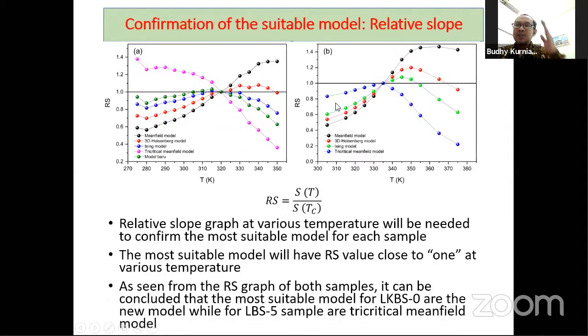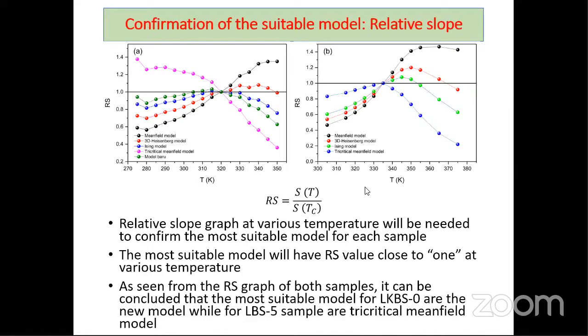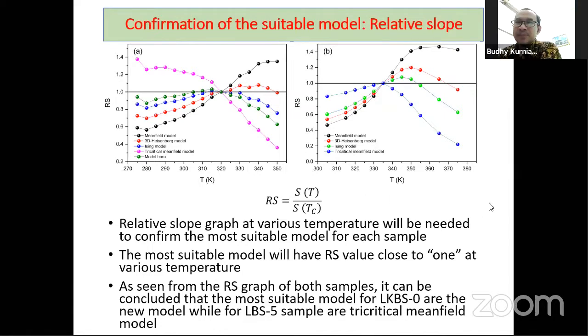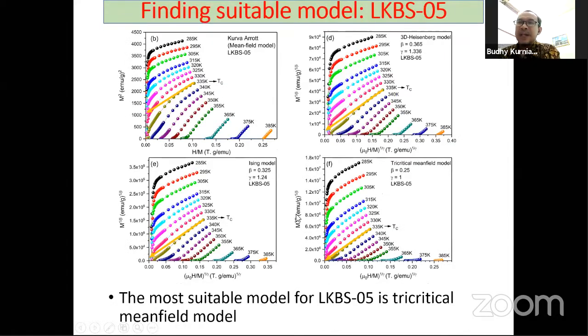So what we found: we find the suitable model for LKBS 0.05 and also LKBS 0. From this we get the gamma and beta for the sample.